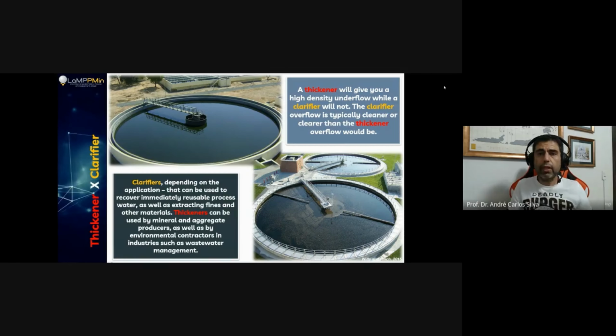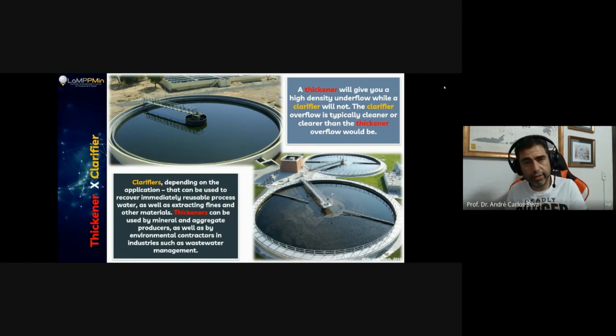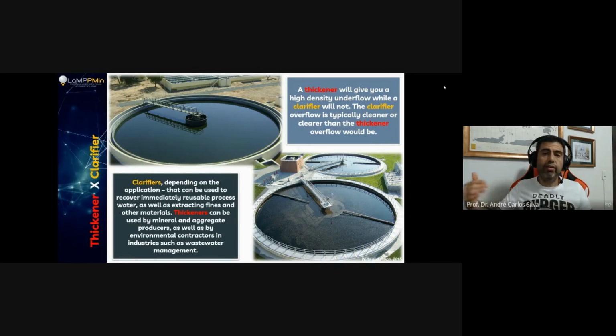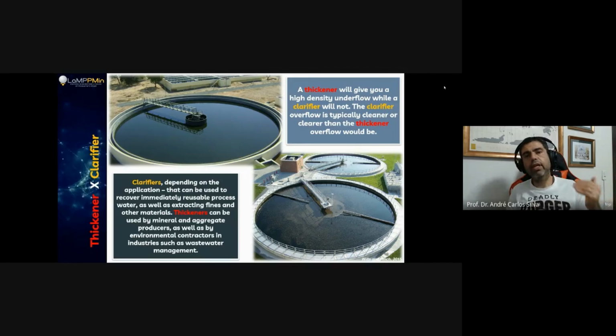However, with the thickener, my focus now is on the solid particles, the solid fraction. So now I want to increase the solid content in my underflow. By doing this, I'm going to eventually lose solid particles in the overflow. So if we're working on a water treatment plant, it's going to be quite regular if you have a clarifier and you want 0% solids on your liquid phase. Normal. And then you're going to have something like 5 or 10% solid content on your underflow. But if you go to a thickener, you're going to have something like 1 up to 3% of solids in your overflow, but you want your underflow as thick as possible.